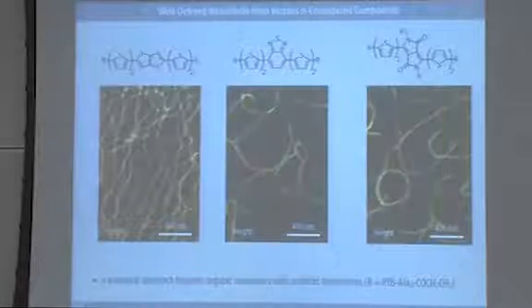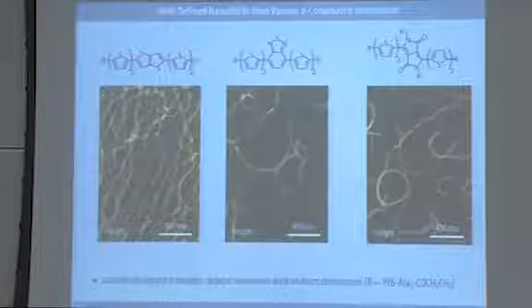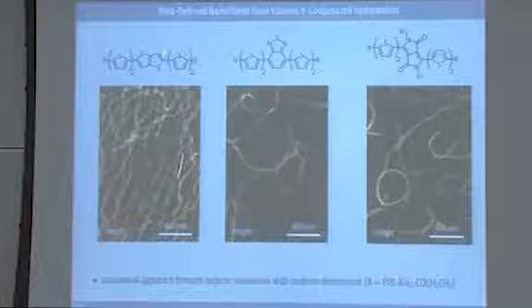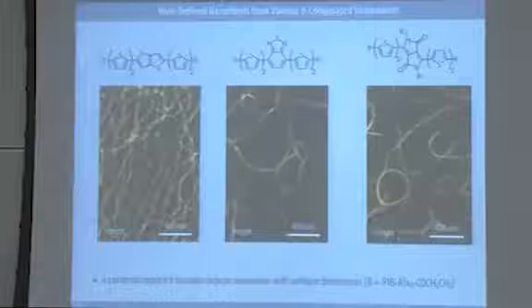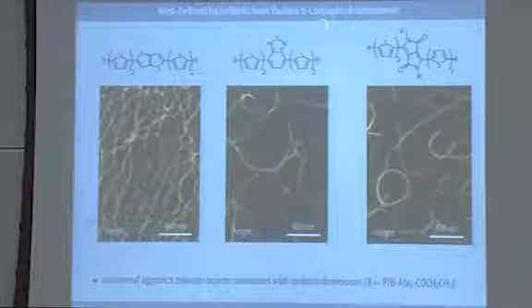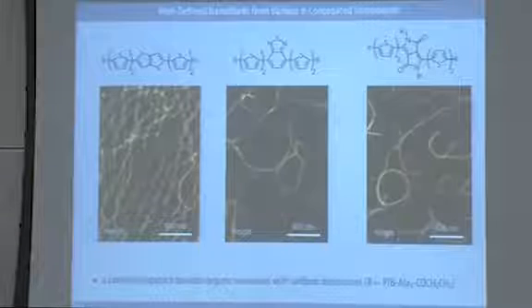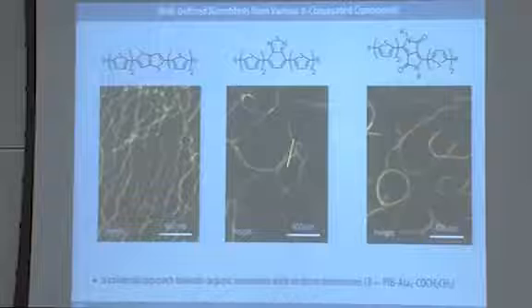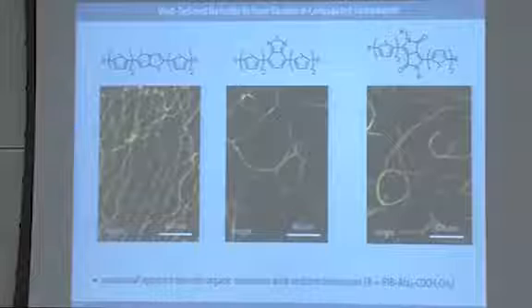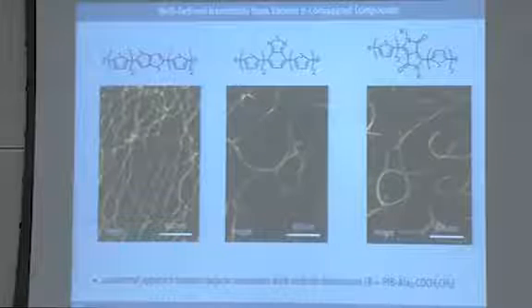And to conclude this story, this is really a universal method to obtain nanofibrils. Not in all cases are they as well defined as I've shown you. We need to work on that. These are very fresh results from a new PhD student in my group who sent me the results 2 days ago. So in this case, we exchanged the oligothiophene core for certain other core elements which we want to use to tune the electronic properties of the nanowires. But you see that this will also influence how these molecules self-assemble. So we need to play a little bit more with thermal annealing in solution and the actual preparation of the solutions in order to obtain better defined nanofibrils in this case.